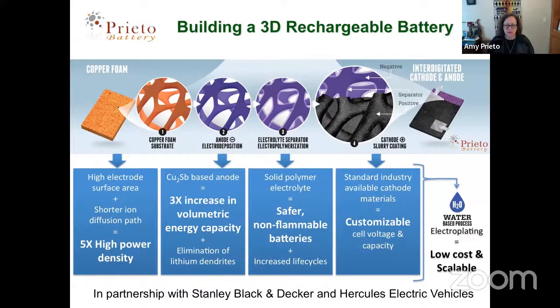These are directly deposited intermetallics. They were chosen because they have very high capacities for lithium, but more importantly, they're really good metals. So that means we don't need to add any binders or additives. They can be used as the working electrode for the next piece, but also they dissipate heat very well, which is important at high power conditions. I'll tell you more about copper antimonide, which is the main anode I'll talk about today.